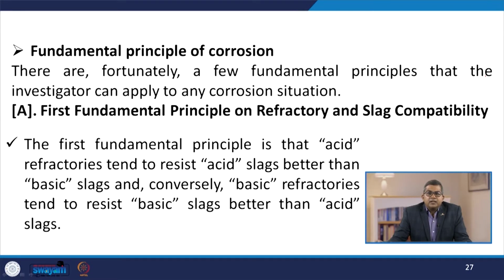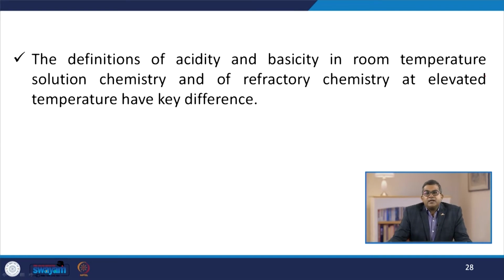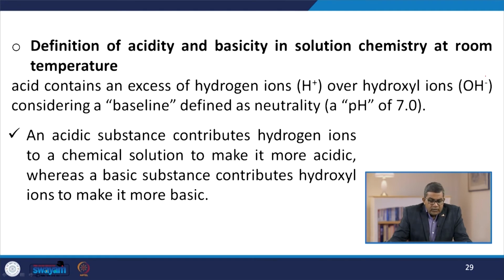Now, while we are discussing corrosion, let's talk briefly about the fundamental principles of corrosion. There are, fortunately, a few fundamental principles that the investigator can apply to any corrosion situation. Now, the first fundamental principle is on refractory and slag compatibility. The first fundamental principle is that acid refractories tend to resist acid slag better than basic slag, and conversely the basic refractories tend to resist basic slag better than acid slags. The definition of acidity and basicity in room temperature solution and in refractory chemistry at elevated temperature have a key difference. Now, the definition of acidity and basicity in solution chemistry at room temperature.